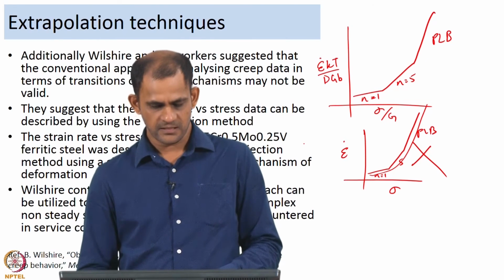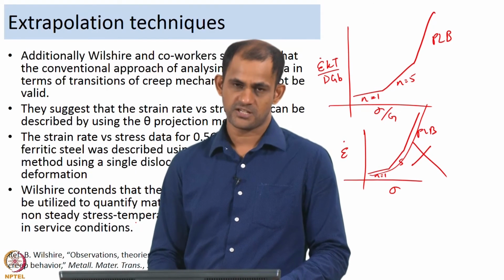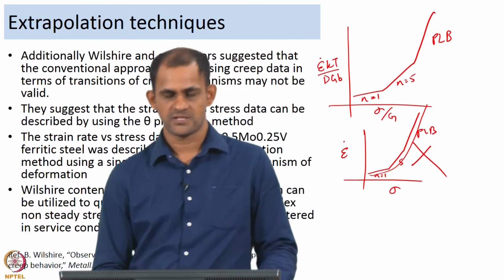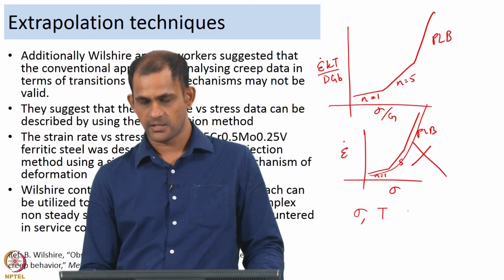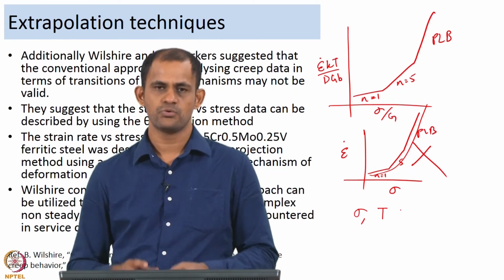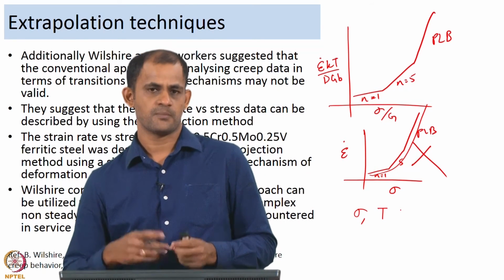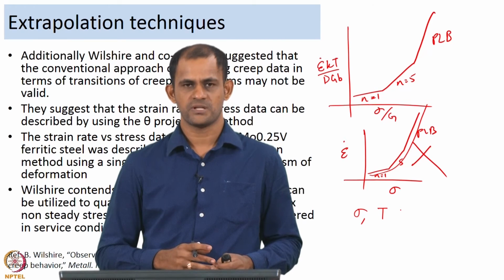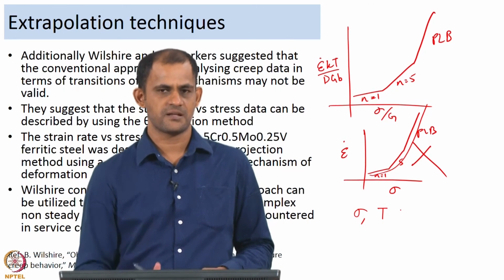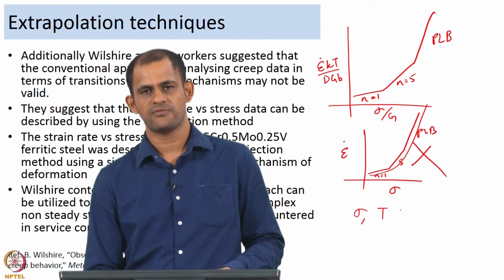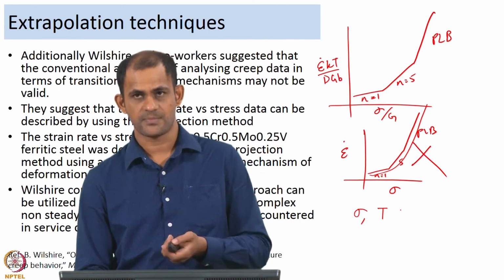So, Wilshire contends that the theta projection approach can be utilized to quantify material behavior in complex non steady stress and temperature conditions encountered in service. All the modeling of creep life assumes a constant stress and temperature during operation, but it is rarely true because materials undergo thermal fluctuations as well as probably change in stress conditions during service. That is why your creep modeling should account for that, and Wilshire says that the theta projection concept can be a better way of modeling the creep performance under these complex non steady stress temperature conditions.